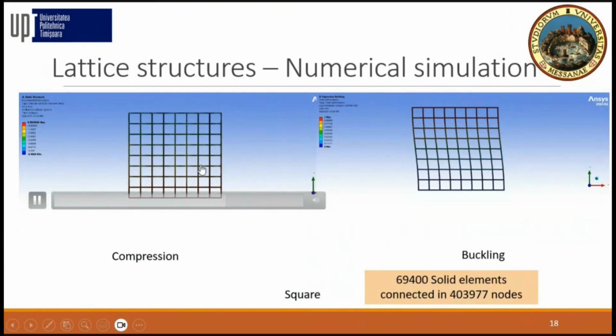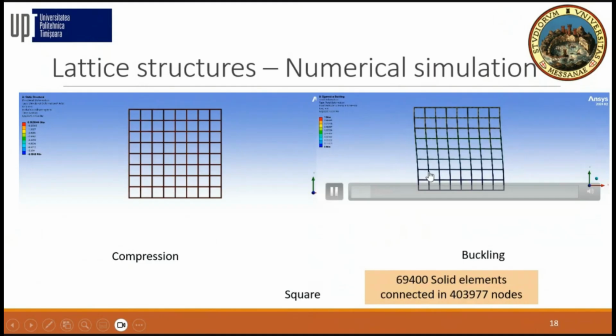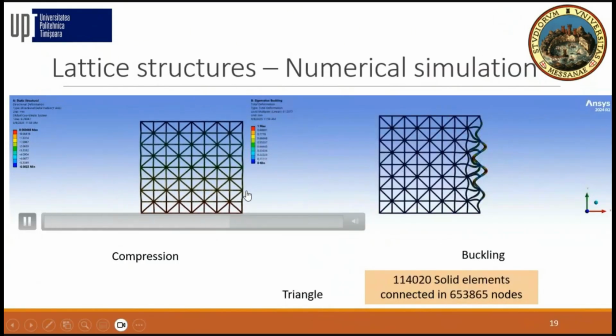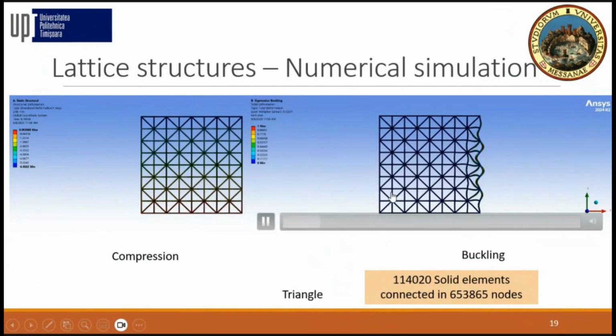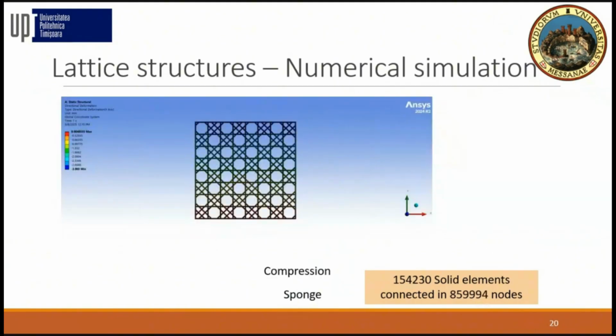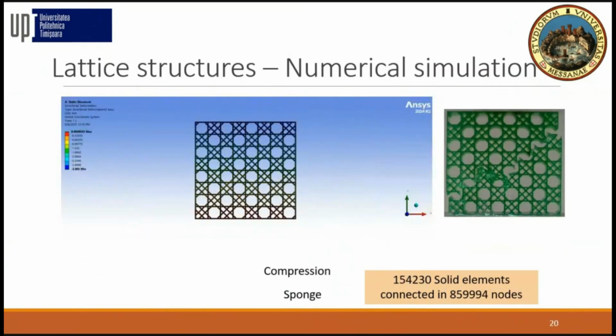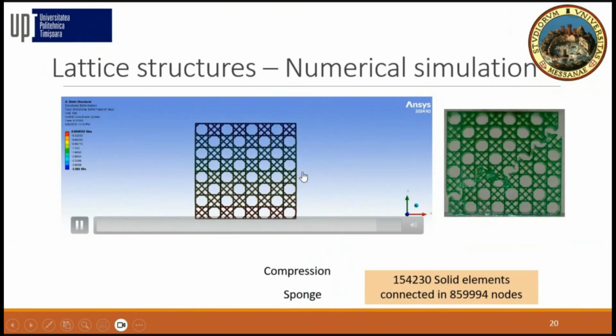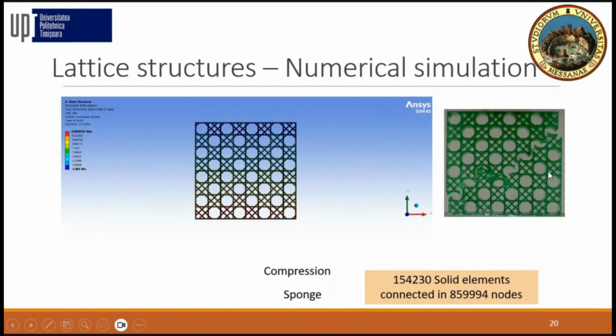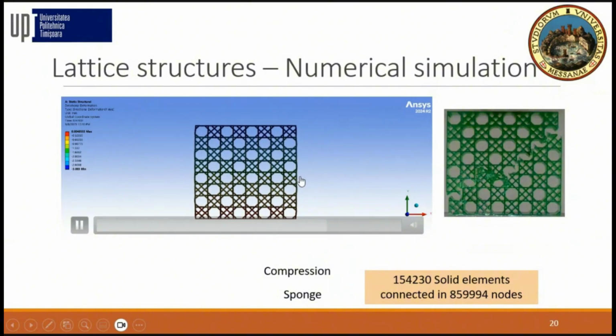We simulate the compression test, the buckling, for the square specimen. We use ANSYS, we block the displacement down, and we impose a displacement on the top edge. So this is the compression test, and this is the buckling test, where you can see we have local buckling on the edge of the specimen. And this is the sponge-like structure where there is no buckling, and the failure is at 45 degrees, the struts in the 45-degree orientation, so this band of deformation is broken.